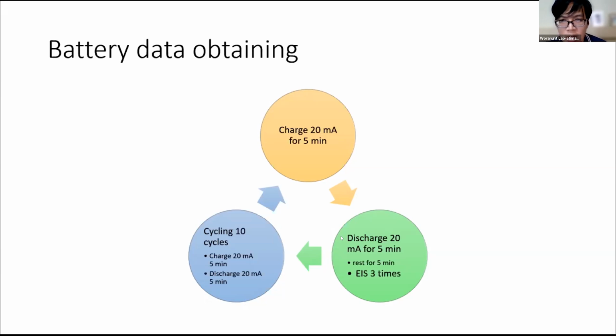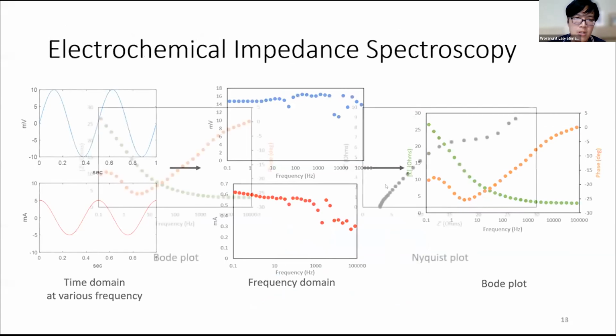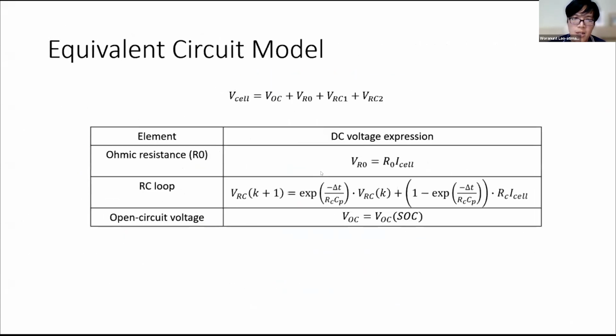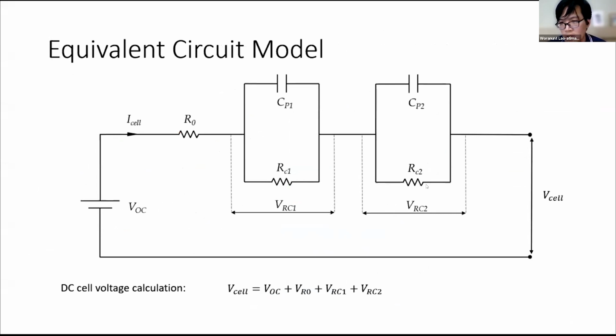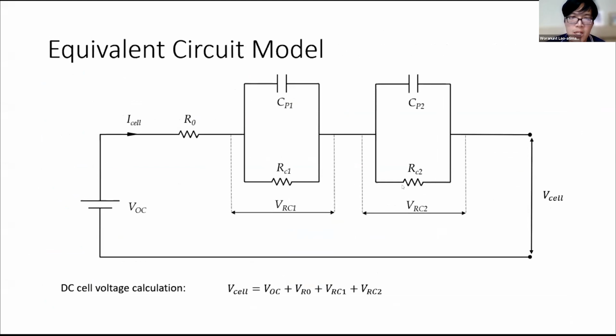Actually, we can use various types of model to fit the result of the test. But because I would like to convert the ECM into the LPV model, the reason that I use second order is because it represents the structure of the battery clearly. We have one RC loop, which represents one electrode, and the second RC loop represents the other electrode. The first loop, which provides the faster response, represents the zinc electrode, which is usually faster than the air electrode. So the second RC loop represents the air electrode.